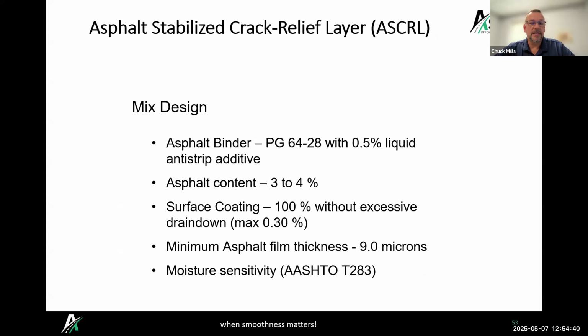Typically, we're using the PG 64-28 binder with a 0.5% liquid antistrip additive. Asphalt content is 3 to 4%. So it's really kind of like a low asphalt content porous mix. And the idea is that as that fracture energy is coming up from a joint or a crack below, it's going to dissipate that rather than letting it go straight up.